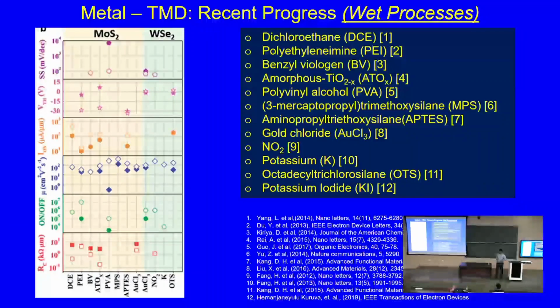And what most of these people did: you take any of these salts, you make a solution, and you will have certain ions. Because of the electronegativity difference, there will be a certain charge transfer. So they make the transistor, they make the contact, then they dip it, then they measure the resistance, and they show that the resistance has gone down, problem solved, right? So when you make the transistor, you have the contact and this edge with the 2D material. These ions go and stick at the edge, and that is where they lower the gap between the Fermi level of the semiconductor and the metal, and that's how the transport gets better.